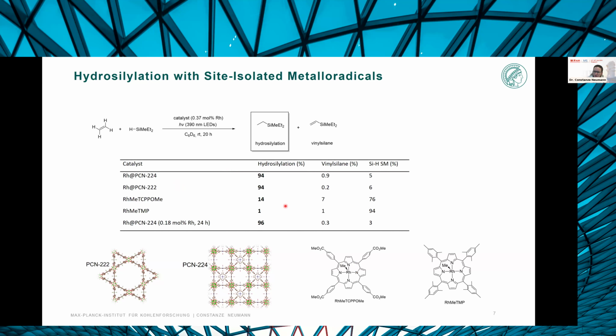Then we figured maybe that's not a very fair comparison because this molecule can actually dimerize in solution. So the concentration of the rhodium-2 that would be available to carry out catalysis would be very low. So we used this system in which there's steric protection available, so that you actually have the rhodium-2 as a monomeric compound in solution, but that actually decreased the catalytic efficiency of the system. Whereas with a MOF catalyst, you can drop the catalytic loading in half and still get very efficient reactivity after 24 hours with over 500 turnovers.